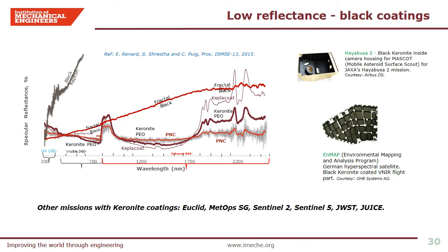This slide shows reflectance of the most widely used commercial black coatings in space. It is important that coatings offer predictable properties throughout the mission, and Keronite black PEO is shown to offer highly stable and favourable specular reflectance values at various wavelengths. Some examples of the black PEO coated components used in various space missions including Earth observation and environmental mapping satellites are shown. Satellite parts are often of highly complex shapes requiring low reflectance black surface and minimised stray light, while giving good thermo-optical characteristics in terms of α and ε. Specific challenges include sharp edges, complex masking requirements, thin ribs and deep pocket features, presenting enormous challenges for most surface technologies, especially those with line-of-sight requirements. For such situations, an electrolytic PEO process can offer unique solutions.